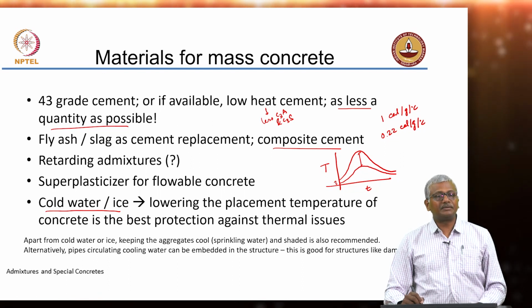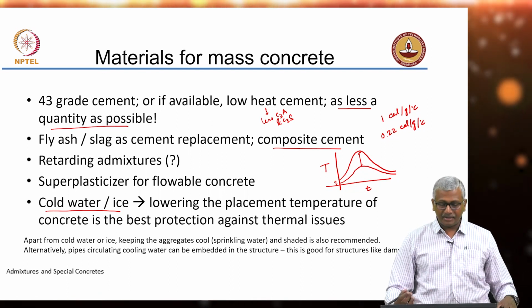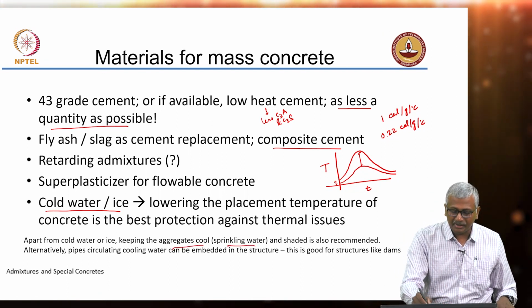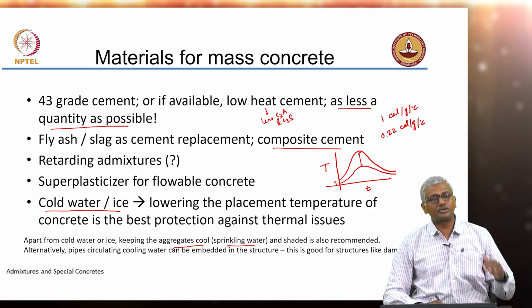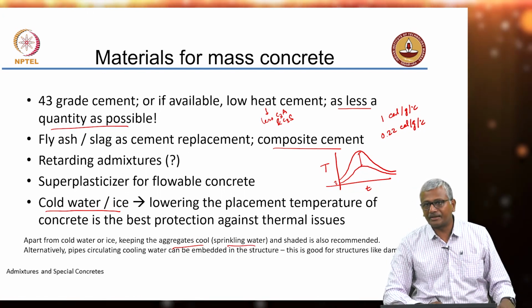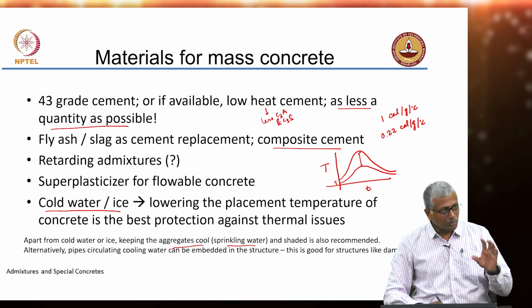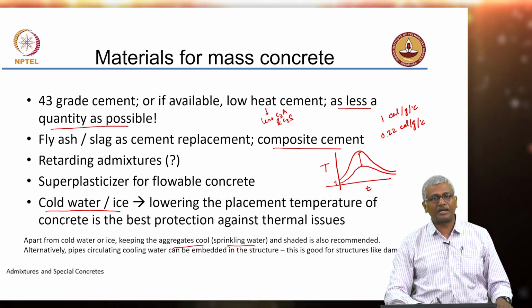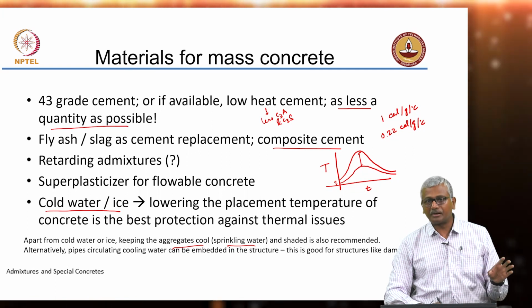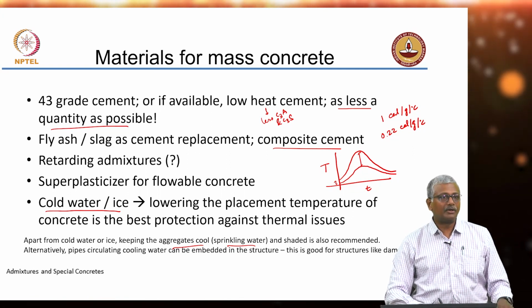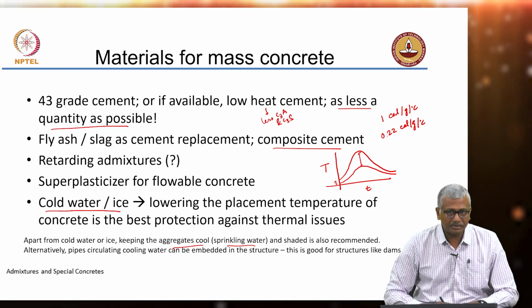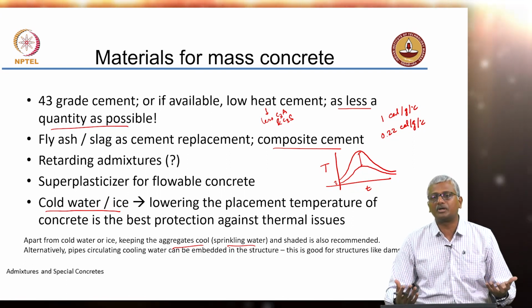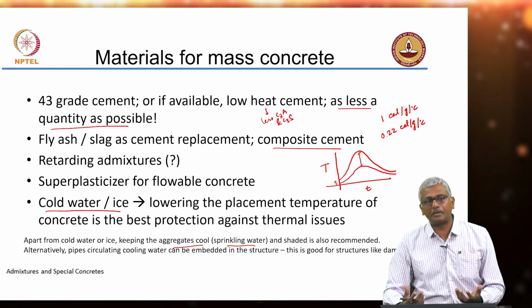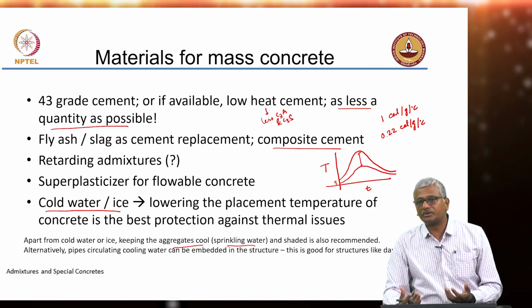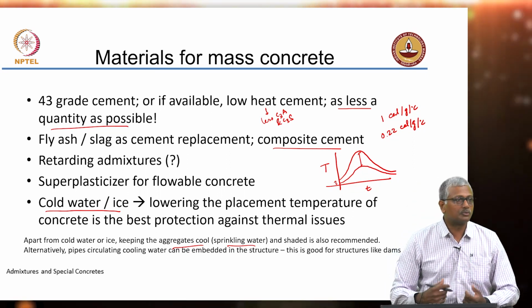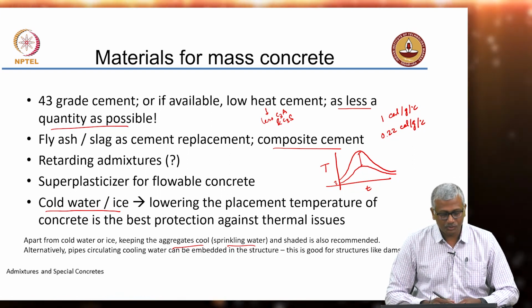But the other materials which are lying out in the open, like aggregates, you can keep the aggregates cool by sprinkling water and also providing a shade over the aggregates as much as possible. In good quality construction sites, the batching plants are planned with sprinklers and with shade in place to ensure that the aggregates don't get very hot themselves, because aggregates are present in very large quantity. No? So even if they have less specific heat capacity, the quantity that you use is significant, because of which you want to bring down the aggregate temperature also.